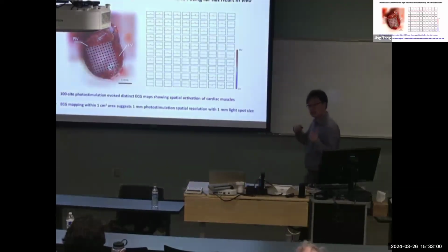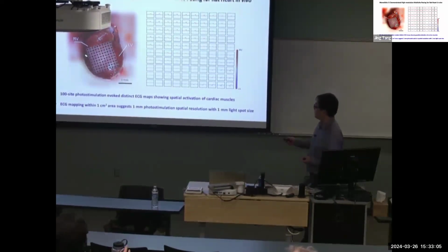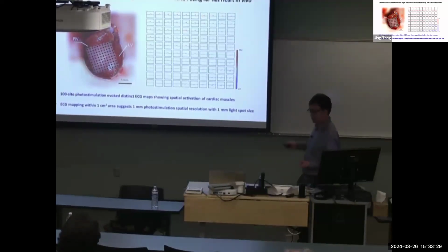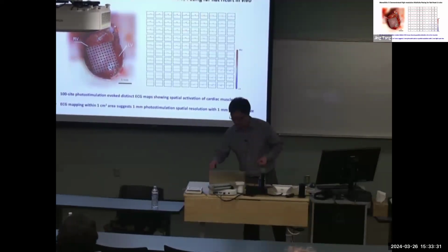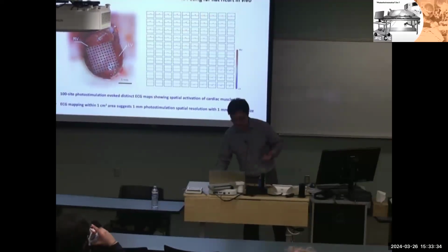Now we can even scale this up, right? So now you have a monolithic membrane placed here. The dots are artificial, they're not real dots, this is label location. But now you can stimulate up to 100 different sites, with the membrane placed on the left ventricle and between the left and right ventricle. And then you can see that when you hit the light at different locations, there is a slight variation in the recorded ECG signal. This is, by the way, the in vivo, in the live heart configuration. The previous one was the ex vivo, the isolated heart.